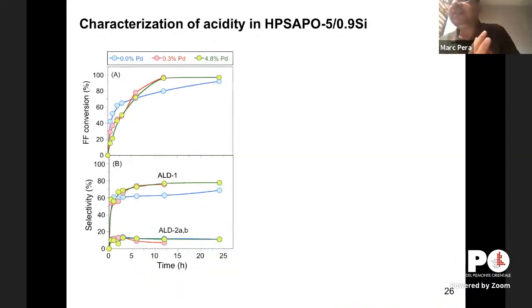Then if you want to design a single reactor process, we need to put the second catalytic center, the redox center. If you want to do hydrogenation, we need to put palladium in our case. And the first thing we do is to see, well, if you put palladium, what happens with the aldol condensation? Are we generating new sites, acid or basic? So the answer is that in our case, no, more or less. What we see is that the aldol condensation follows a similar pattern in terms of conversion and selectivity.